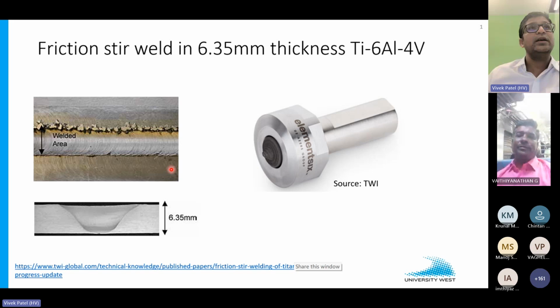These three categories of materials are quite new, and for that a new tool development needs to be done. You need a very hard tool material, and not only a hard tool material, but you also need to process it, to machine down to small features on the probe and the shoulder. So a lot of research is happening. You can see that Element 6 has developed a tool material to weld steel, and it's a new tool material. It's like a synthetic diamond